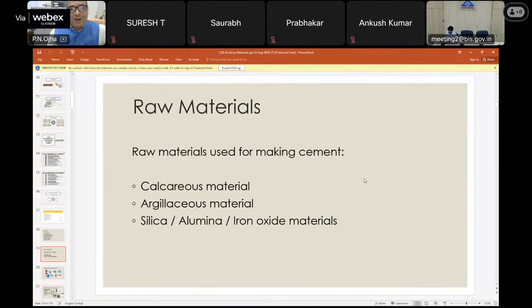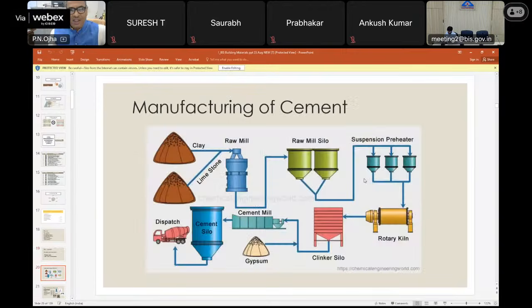So I have explained the raw materials used for the cement: calcareous, argillaceous, and silica, alumina, iron oxide, and all that. And this is the manufacturing. You can see there is a raw mill in which it is ground like a powder, then it goes to the raw mill silo, and from this silo it goes to the preheater, where some calcination happens, CO2 comes out, and then that powder material goes to the kiln, as I said.